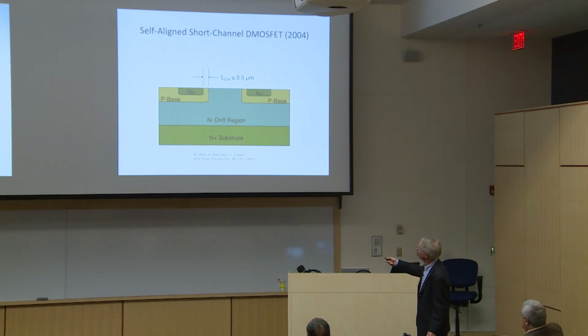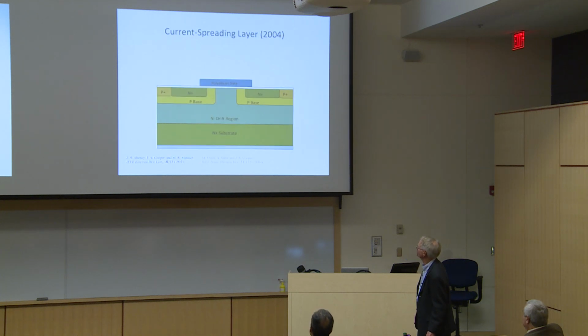Now, the next step, after we've stripped all of this stuff off the top, we grow a thermal oxide layer. This is going to be a gate oxide. We put down another polysilicon layer to form the gate, and that looks like that. So it's beginning to look like the real MOSFET. But now another thing that we added in 2004 was what we call a current spreading layer. And this is a region near the top of the N- layer that's more heavily doped.